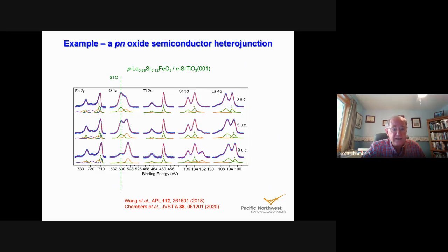On the oxygen 1s, you have 2 peaks, right? That's because you have oxygen in 2 different materials that have different electrostatic potentials. The lower binding energy feature is the oxygens in the STO substrate. The higher binding energy feature is the oxygens in the LSFO. If you look at the titanium, same thing. The reason for this is there's a little bit of intermixing at the interface.